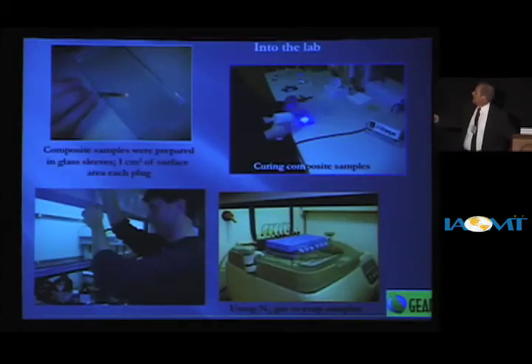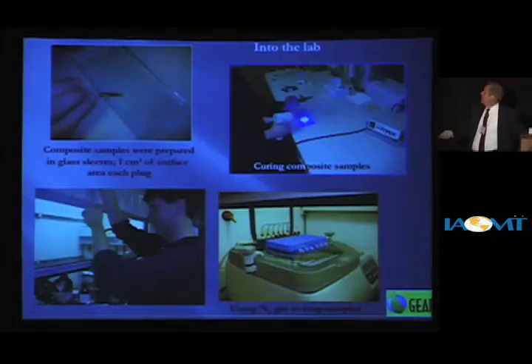So here was the deal. I had these glass sleeves specially made up so that they had an inner diameter and a height of 2 millimeters, so that when popped out of that glass sleeve, the plug was 1 square centimeter surface area. So they all have the same surface area. In the second study, I also weighed the mass of each one so that I could put it on that other scale of, say, nanograms of BPA leached out per milligram of composite. And we can put that data also on the website.